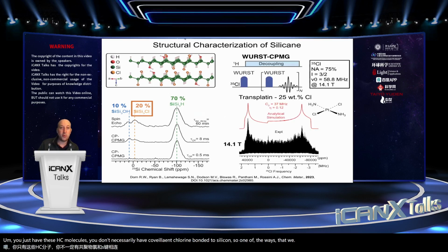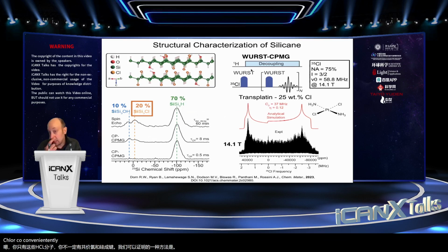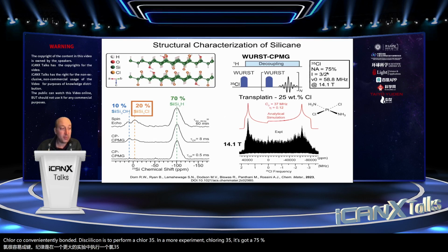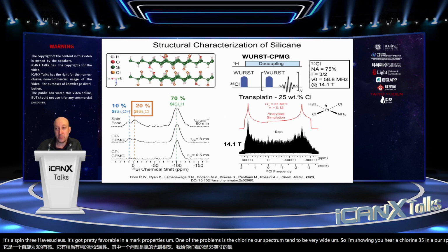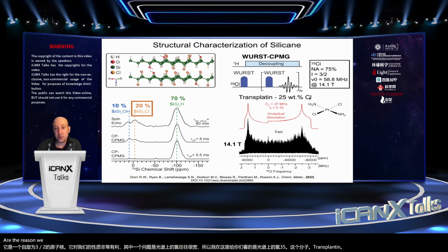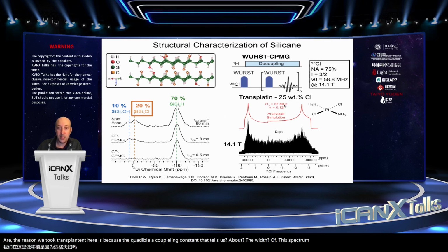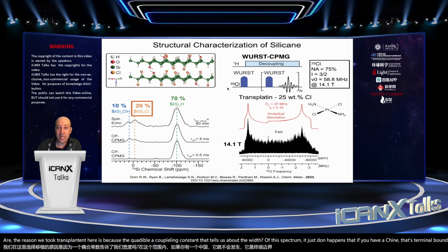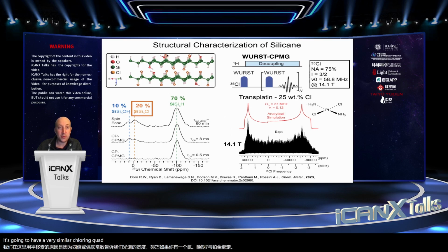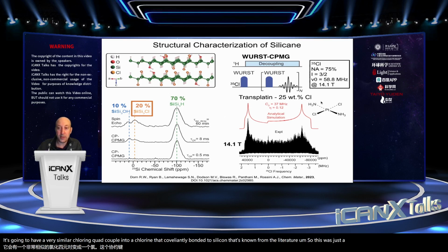So one of the ways that we could prove that we have chlorine covalently bonded to silicon is to perform a chlorine-35 NMR experiment. Chlorine-35 has a 75% abundance. It's a spin 3/2 nucleus. It's got pretty favorable NMR properties. One of the problems is the chlorine NMR spectra tend to be very wide. So I'm showing you here a chlorine-35 NMR spectrum of this molecule, transplatin. The reason we took transplatin here is because the quadrupolar coupling constant tells us about the width of this spectrum. It just so happens that if you have a chlorine that's terminally bound to platinum, it's going to have a very similar chlorine quadrupolar coupling constant to a chlorine that's covalently bonded to silicon. That's known from the literature. So this was just a model compound for us.